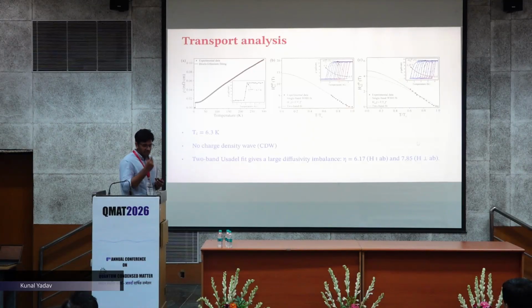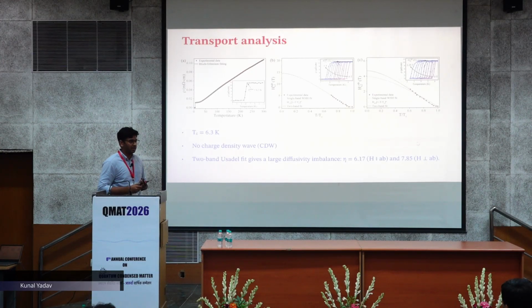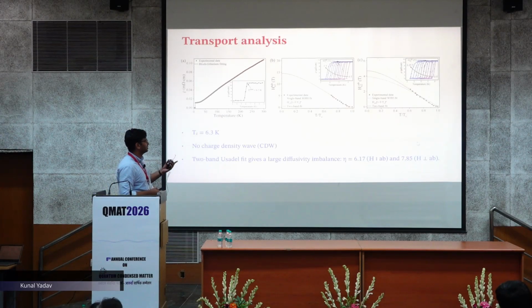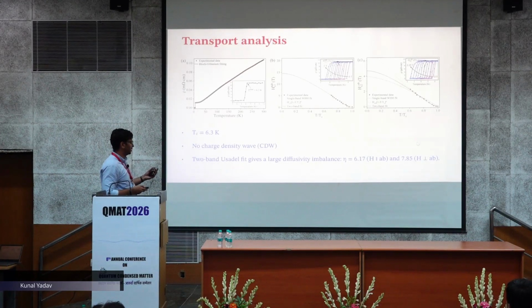Okay. Then we proceed to the transport analysis. We see here that the Tc is 6.3 K, and also there is no CDW in the resistivity from 0 to room temperature, and this shows that there is no CDW ordering. And we have also fit the Hc2 data with single band and two band fittings, and the single band is not well fitted with the data due to the pronounced Hc2 curve at higher temperatures. So a two band Usadel model gives a very good fitting with a large diffusivity imbalance, which is 6.17 and 7.83.